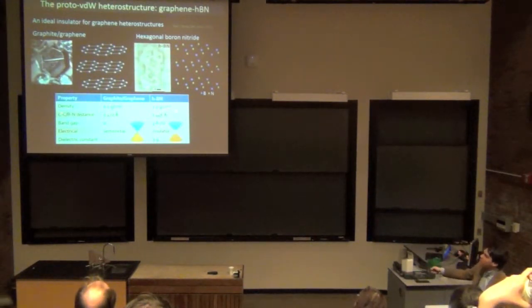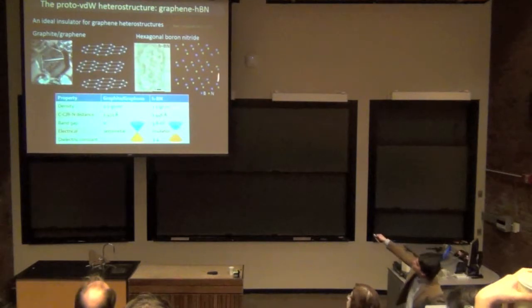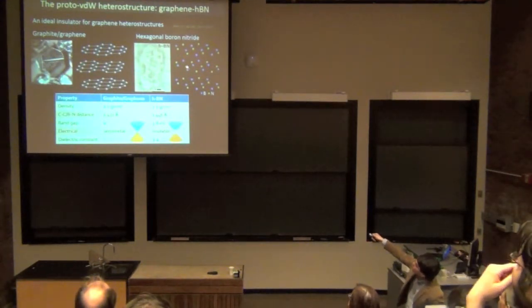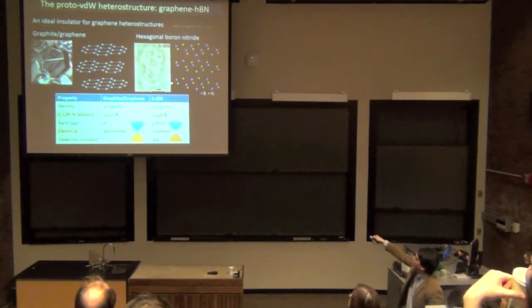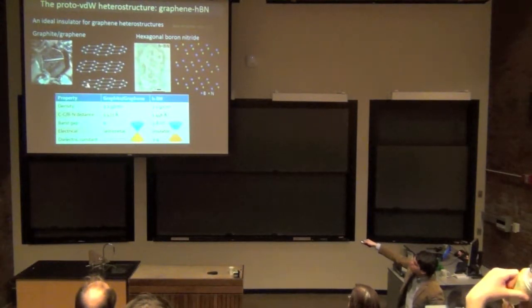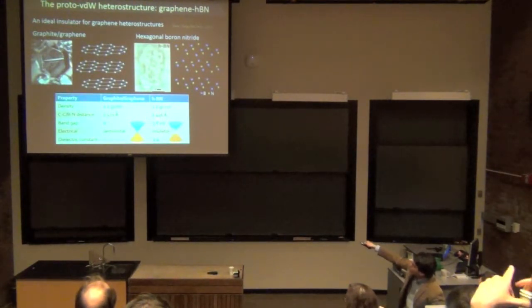Basically, it has the same density and almost the same bond distance. I don't know if you can see that, but this is basically the same structure as the graphene here. It's this hexagonal lattice, but instead of having the carbons on these A and B sublattices, it has a boron and a nitrogen on the sublattices. And so this distance between these two is only different by about 2%.